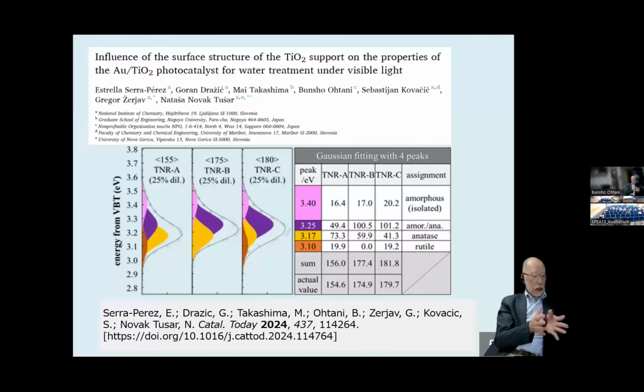For example, a titanium oxide sample. This is a collaboration work with Slovenian researchers. This peak, the blue-violet peak, is important. So for the photocatalytic activity, that is amorphous and anatase peak, if the proportion of this peak is high, the photocatalytic activity is high. So amorphous is important. Previously, we thought that amorphous phase is not so good because it may induce the recombination of electron and positive hole. However, this result shows that amorphous phase is important.